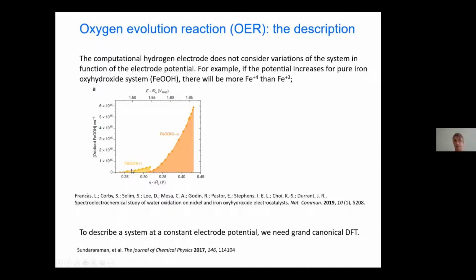And to describe systems at constant electrode potential, we would need another type of theoretical approach, and this is called grand canonical DFT. But even this would not be complete yet, because many of the species that we have to describe have a multi-reference character. So there is still plenty of theoretical methodology improvement that needs to be done within computational electrocatalysis research.